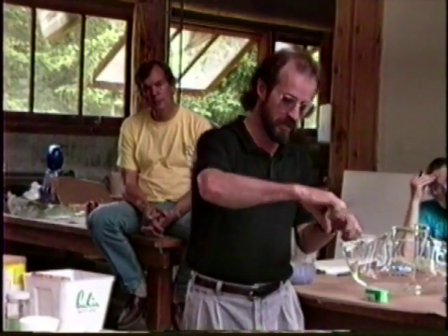Anything bigger than about like that, when you go to full fuse, you're chancing blowing a big hole in it. Another way to do it is to work with 3 or 4 thicknesses. You've got so much weight it won't blow up. But when you've got 3 or 4 thicknesses, it's going to want to spread out. So you need to put a dam around your piece. You can dam your piece with bricks or a metal or whatever, as long as the metal isn't going to trap the glass. It's got to be in sections. Usually I'll put fiber paper in there as a cushion. Then you have to come back and grind and polish the edge. So you can fuse thicker, but to fuse on its own and stay near the shape you want, 2 thicknesses with maybe third layers.